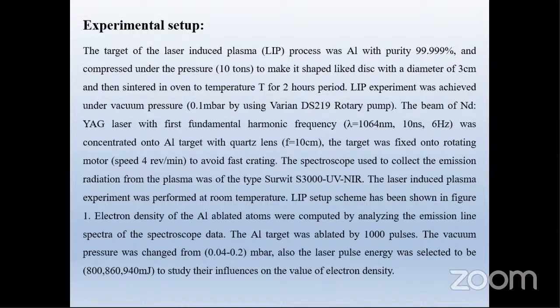The spectroscope used to collect the emission radiation from the plasma was of the type Surwit S3000, UV near IR. The laser-induced plasma experiment was performed at room temperature. The laser-induced plasma setup scheme has been shown in figure 1. Electron density of the aluminum ablated atoms was computed by analyzing the emission line spectra of the spectroscope data. The aluminum target was ablated by 1000 pulses. The vacuum pressure was changed from 0.04 to 0.2 millibar. Also, the laser pulse energy was selected to be 800, 860, and 940 millijoule to study their influences on the value of electron density.